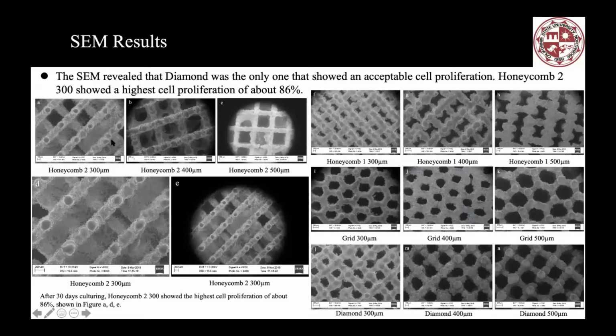Then you can see here A, B, and C, this is honeycomb 2, the 300, 400, 500, right? This shows the highest cell proliferation, about 86%, from A, D, and E. So this is honeycomb 2, because D and E are the actual images of honeycomb 2, 300 micron. B and C are 400 and 500. And for honeycomb 1, the grid and the diamond, they failed in the compression test, but we still put the cells inside and looked at the structure. But eventually we found maybe honeycomb 2, 300 is the most effective one. But this is something I discussed with our partners in biology, right?